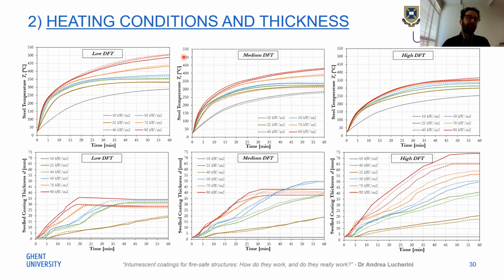So these are some typical results. You can see here on the left, low DFT, the results in terms of steel temperature and swell coating thickness, medium DFT, 2 millimeters, and high DFT, 3 millimeters, in terms of steel and coating temperatures. What is interesting is that for the high DFT, when you have a high thickness, the coating swelled throughout the whole duration of the process, except for the case of 10 kilowatt per square meter, where, as I presented earlier, I was not expecting any swelling. You can see here, in the gray curve for 10 kilowatts, I didn't get any swelling. But in the other cases of high DFT, the swelling continued during the whole process. And the temperature of the substrate, in all the cases, tended to between 300 and 350 Celsius degrees.